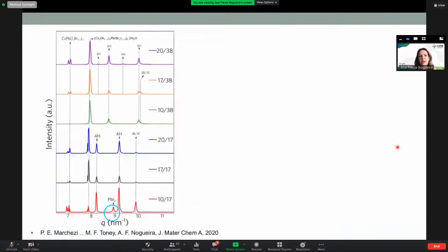It took us a while to identify, but that kind of microrod that you see forming is actually not lead iodide. I was very surprised by that. You only see lead iodide when you have low concentration of cesium and bromide.